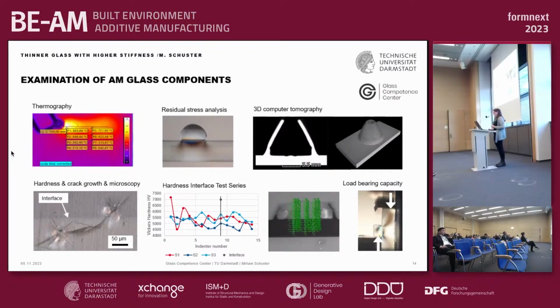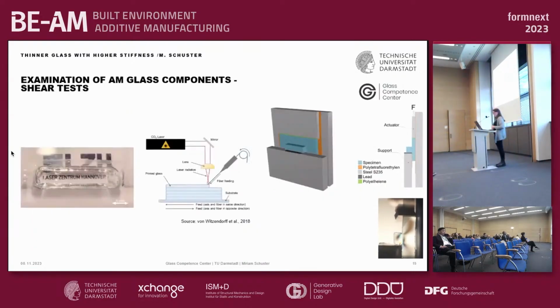We also performed some load-bearing capacity tests. In this case, we have here a shear test, and I want to present this a bit more in detail. So here we had samples. Again, we had a base plate, and on this base plate, a wall was printed, and this printed wall had dimensions of approximately 25 by 6 millimeters and 6 millimeters in height. This wall was printed with a laser glass deposition process, and this was done by the Laserzentrum Hannover.